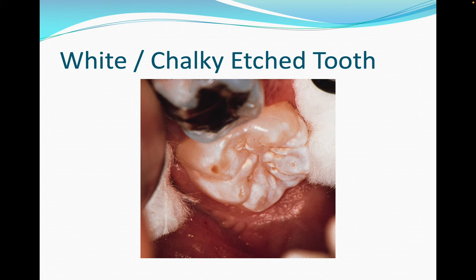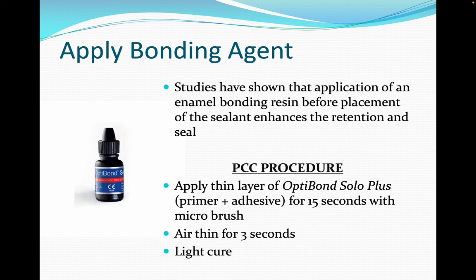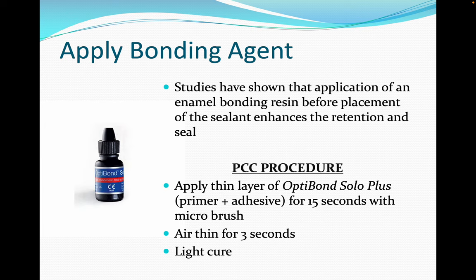Applying a bonding agent is an optional step, though at the time this content was created the PCC procedure was to apply Optibond Solo Plus (a primer and adhesive in one). Studies show that applying an enamel bonding resin before sealant placement enhances retention. Apply it for 15 seconds with a microbrush, lightly air-dry for about three seconds, then light cure.